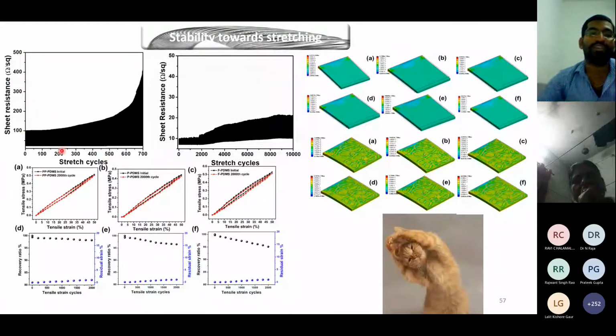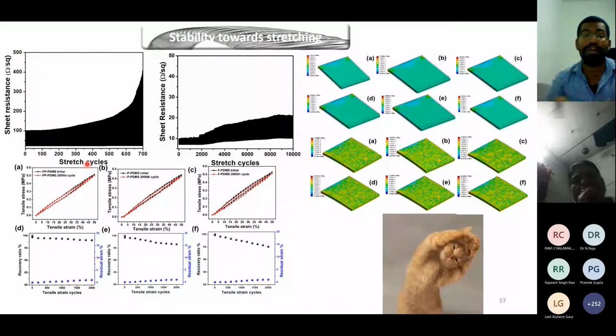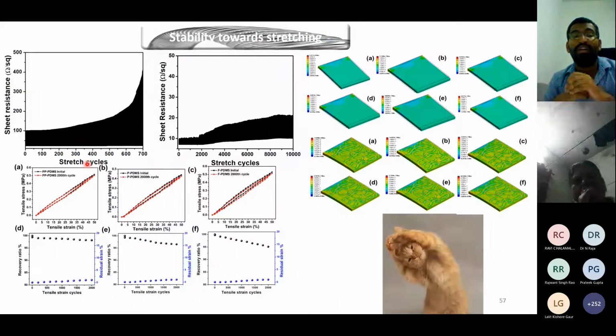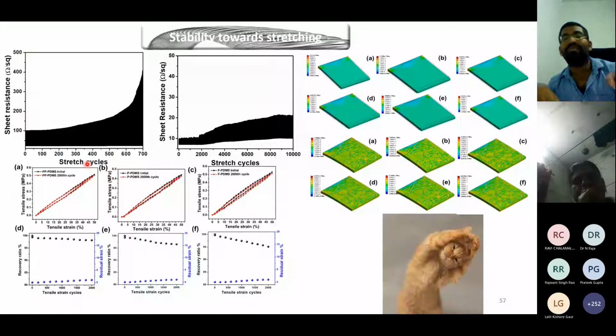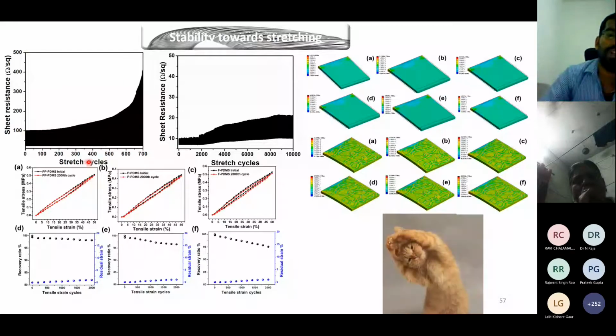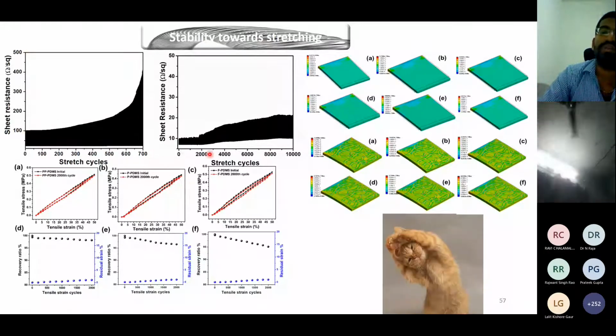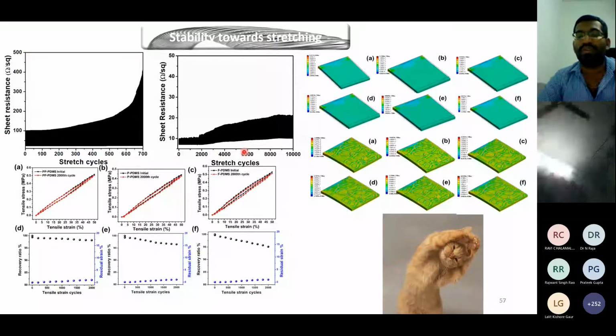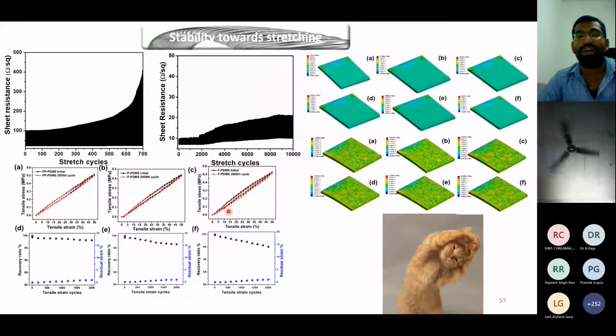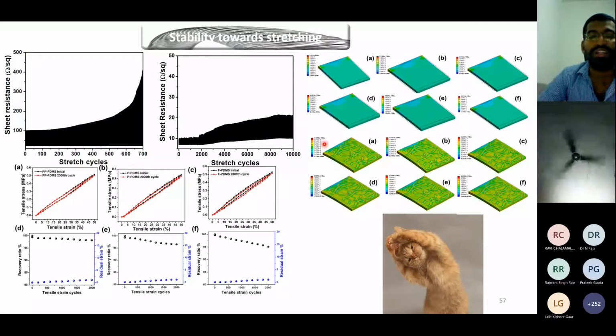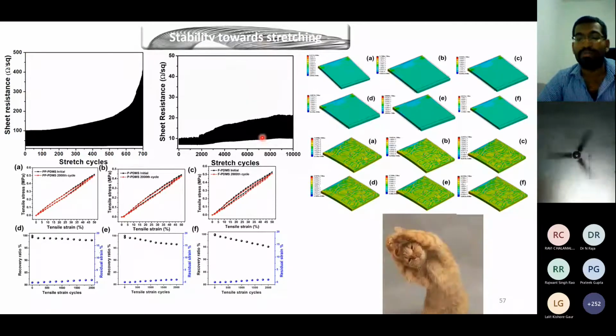Here I'm comparing the stretch cycles. We do the cycles for the two different substrates. One is FPDMS, the other one is PPDMS. Here we are able to see which has very good durability, nearly 10,000 cycles. It's very robust. It's retaining its conductivity. And why this kind of good durability? We are able to achieve very good stability in terms of wearability, because we have this kind of microstructures.